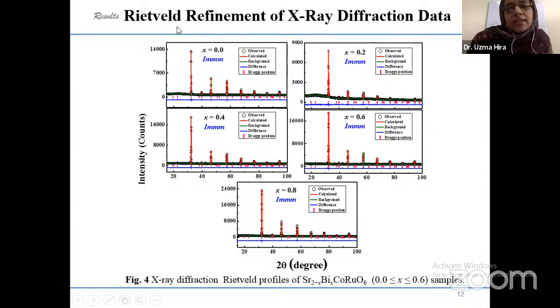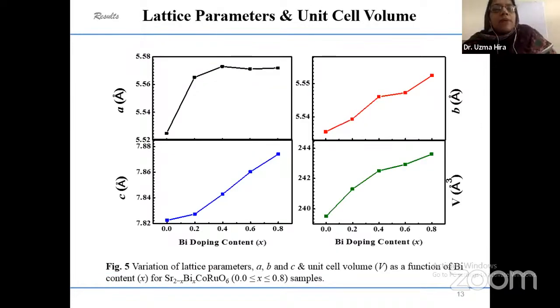And here you can see that the difference line is almost straight, which indicates that our experimental data completely fits with our model. So we have extracted a large number of parameters from this refinement data, and these are the lattice parameters which we have extracted from the refinement data.